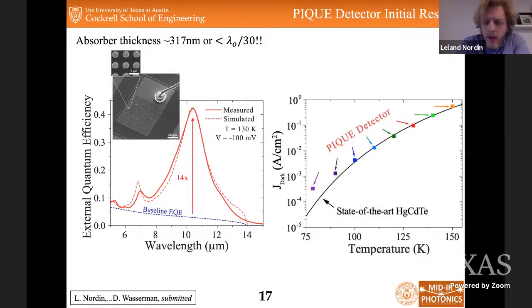And as I mentioned earlier, dark current scales as your absorber thickness. So one would expect with this really, really thin absorber, we'd get a reduction in dark current and therefore a reduction in noise. So shown on the right is actual dark current versus temperature of our PIQUE detectors. And you can see around 130 and 120 Kelvin, we actually are below mercury cadmium telluride, which is the state-of-the-art infrared detector and has been so for the last 60 years. So with this plasmonic enhancement, we're able to realize comparable EQE with lower dark current than state-of-the-art infrared detectors.